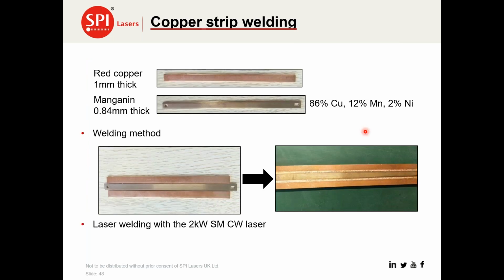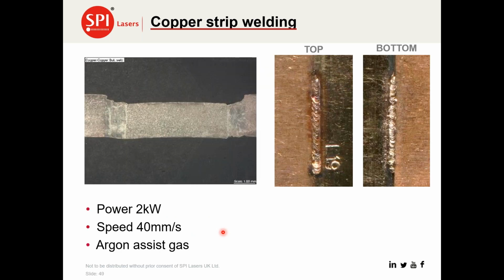There are some interesting applications where we can weld dissimilar materials, and this is one application we did in our lab where we're looking at joining copper and manganin, where we had different thicknesses of materials. We used the 2 kilowatt single mode using oscillation welding, and we got very, very good control of the heat input to create very nice square welds for this particular application.